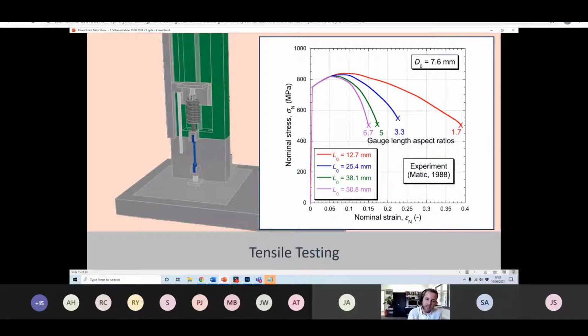But once that necking process starts within the specimen, then the aspect ratio starts to have a very significant effect on the measured test outcome, specifically on the ductility value. So when people therefore cite to you a ductility value, it's often, and I don't mean to be contentious, but it's often totally meaningless. If you search the literature looking for ductility values of a particular alloy, and there's no information about the test specimen dimension, then that information is also meaningless. The only real way that a ductility value can be used is to rank different materials that have been tested using the exact same specimen dimensions. Otherwise, ductility values are actually of very limited engineering utility.